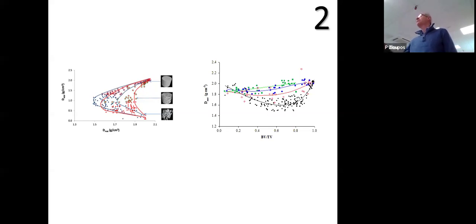The remodeling rate depends on the active surface area, and inevitably, with osteoporosis, where the porosity level increases, you end up with more dense and brittle material. So these struts that are left in osteoporosis at the end, the material has less bone mass and has higher local density, or strut density.